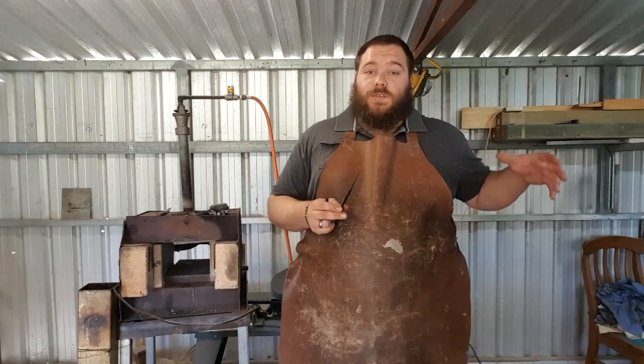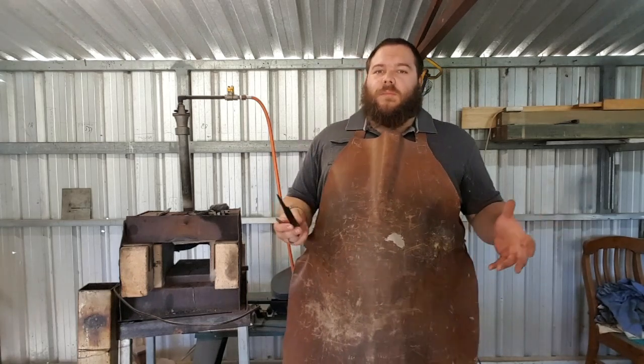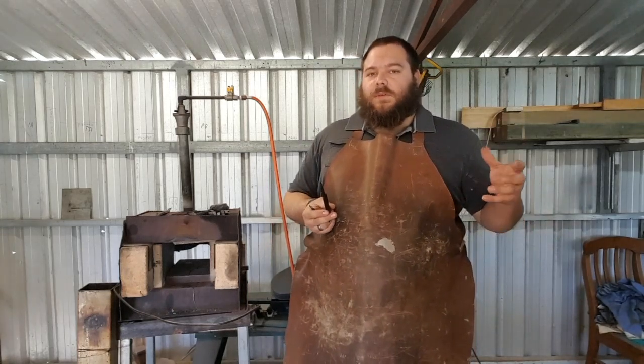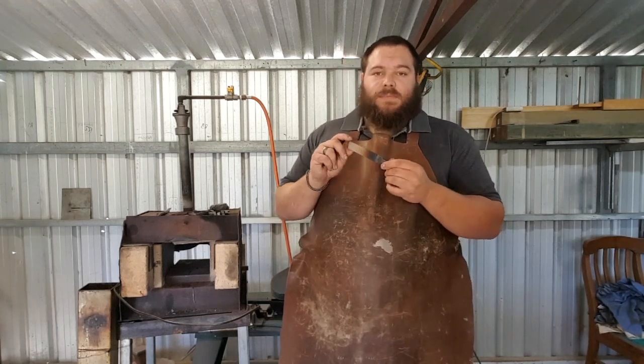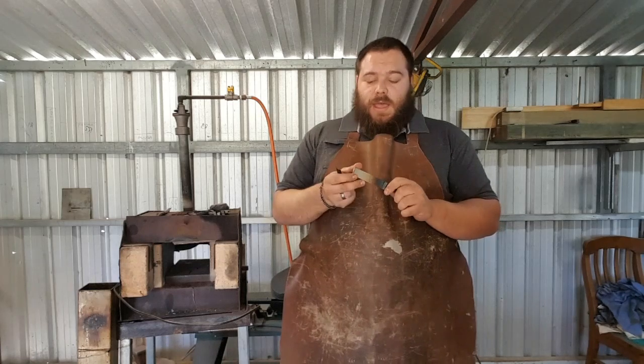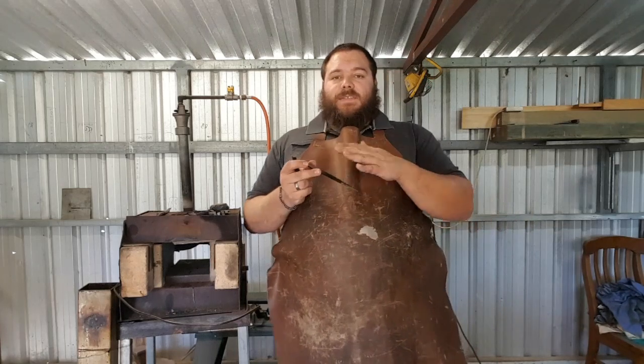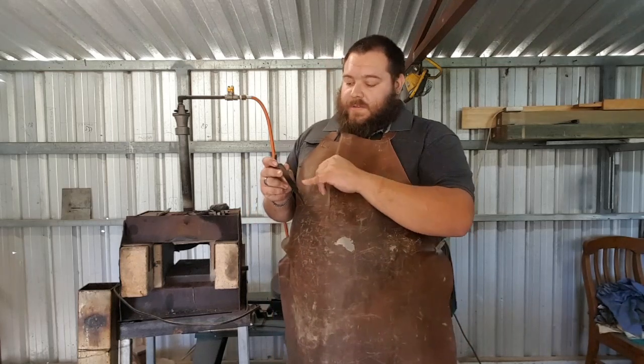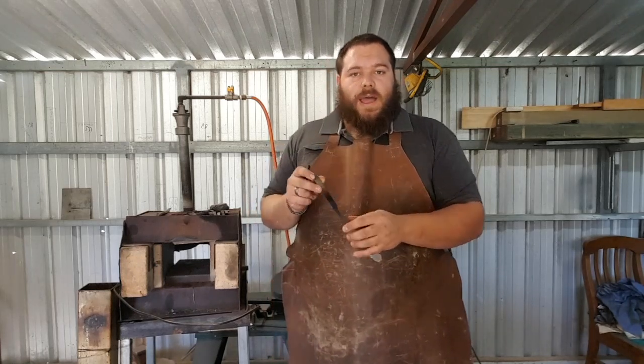That's why most leaves we see are green, but they're not actually green themselves. It's just that that's the only color that reflects off the leaf. The leaves are actually yellow or some form of brown, but they suck in all of the red and the blue and all that kind of stuff, and only give us the green reflection back. So that's the same thing with this. When the oxide layer is very thin, it reflects back the yellow colors in the light that's reflecting off the surface. And as that scale builds up, as that oxide builds up, it slowly darkens and then turns that purple, the blue, and the gray.